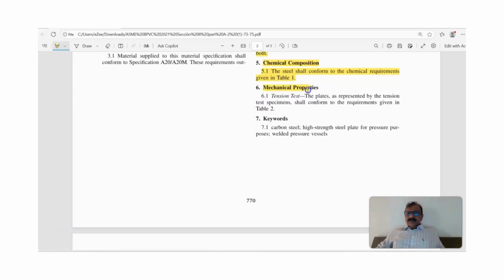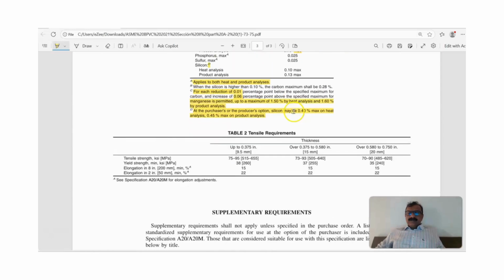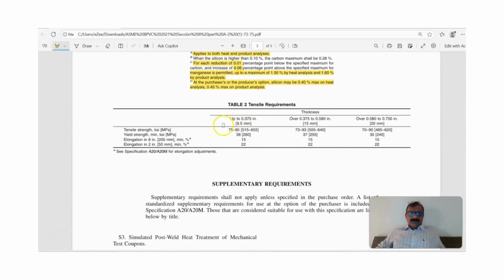Then mechanical properties, only tension test. The plate represented by the tension test specimen shall conform to the requirement given in table 2. We'll see the table 2. And in the specification there are no grades, so there is only one grade. And then you can see there are thicknesses 9.5 mm, then 15 mm, then 20 millimeter. There is range also. Tensile strength decreases as the thickness increases. Yield also decreases as the thickness increases. Elongation remains same. For 2 inch it is 22%.